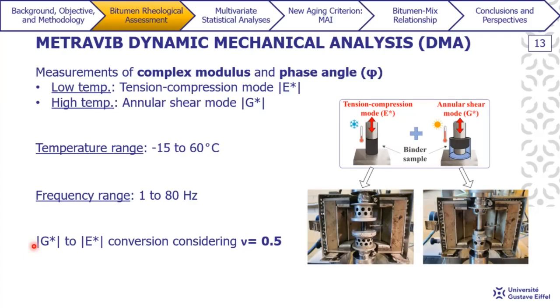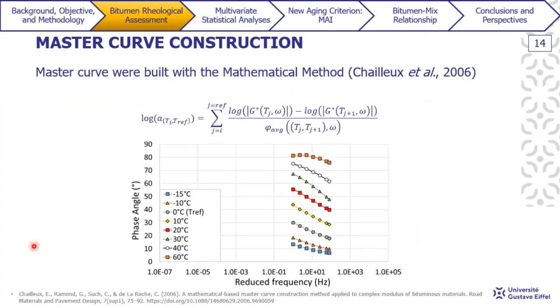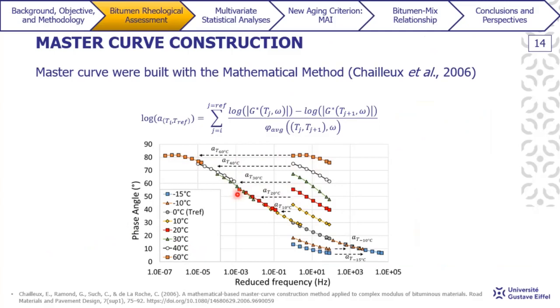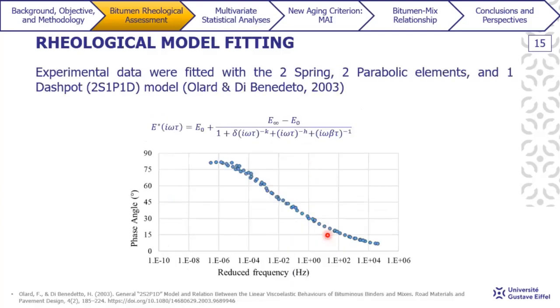And the conversion from G star to E star or vice versa was done using a Poisson's ratio of 0.5. So since bitumen were assumed to be a thermorheologically simple linear viscoelastic material, the limitations of laboratory testing conditions can be overcome in this case by constructing a unique master curve that in this case is pretty much shifting each of these isotherms here from a reference temperature that allows extrapolating the experimental data to conditions closer to those our asphalt mix are likely to be subjected to during pavement service life. And here, this master curve was built using the mathematical method proposed by Chailleux and coworkers.